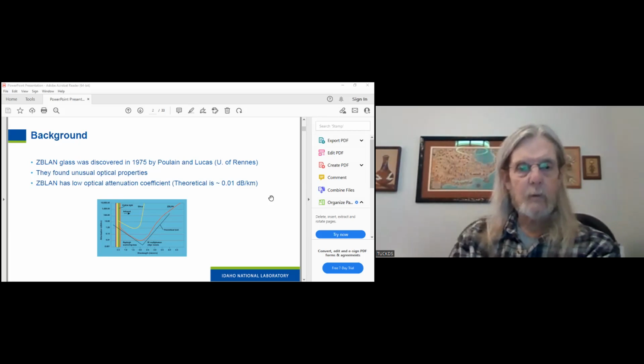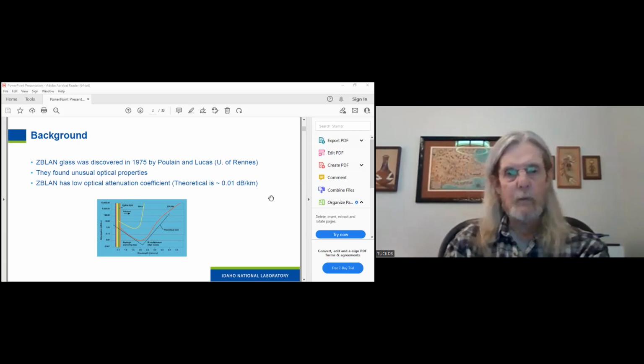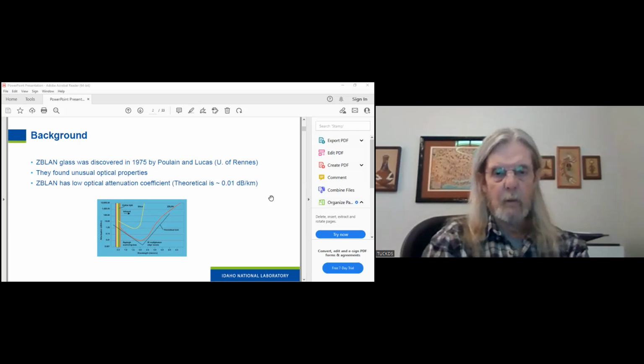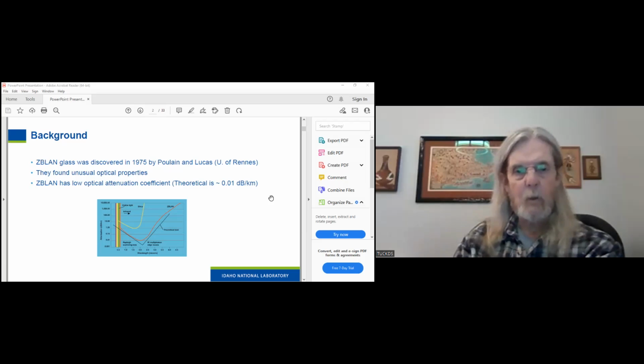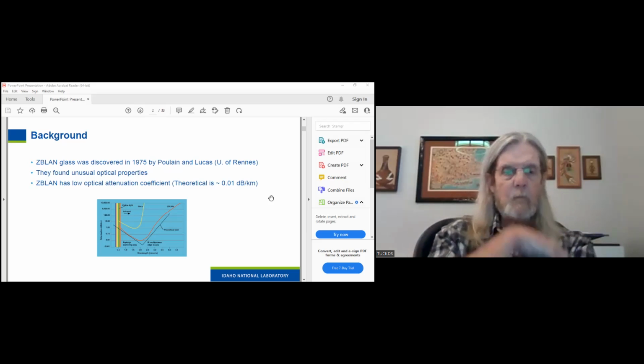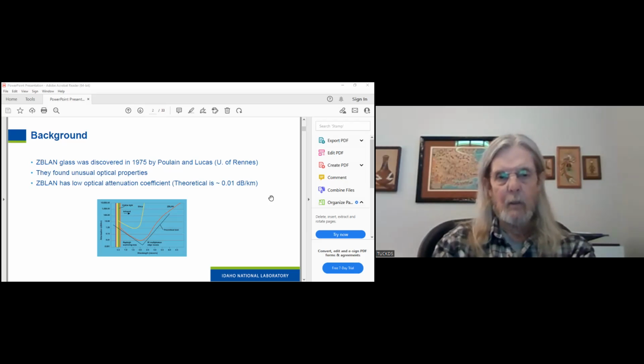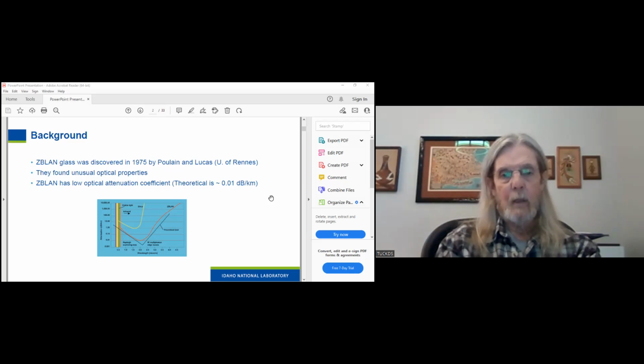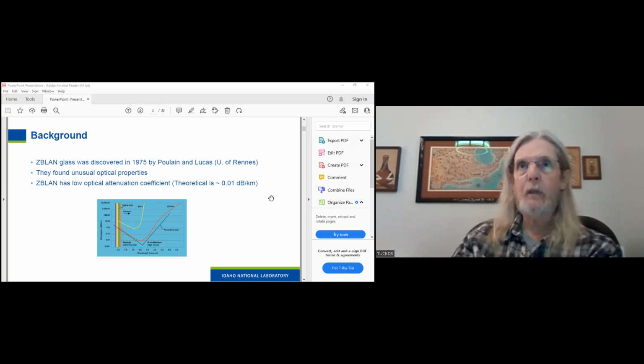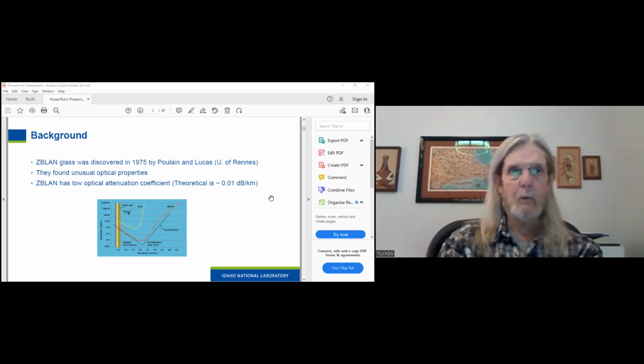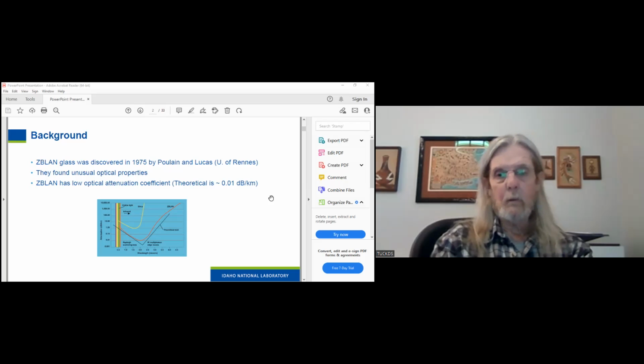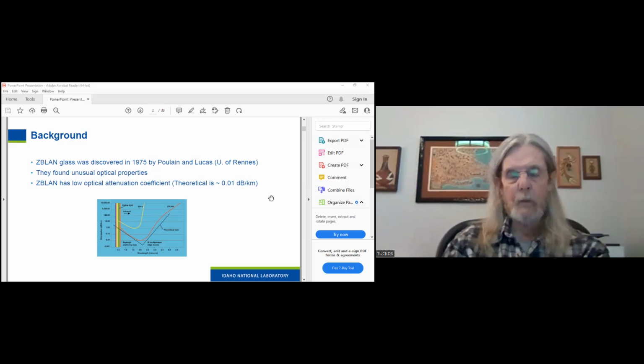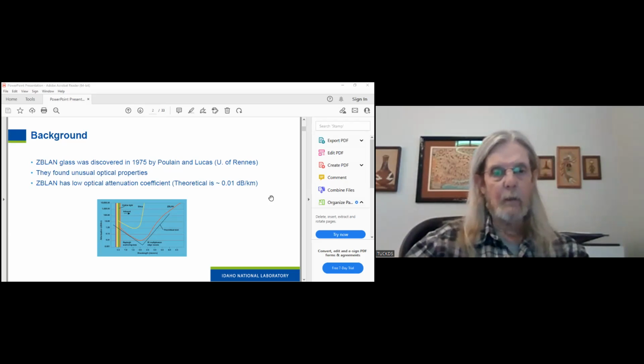And as you can see from the figure, attenuation coefficient versus wavelength for ZBLAN, there's a theoretical curve there, and also what has been measured to date versus fused silica. And one of the interesting properties of ZBLAN is that it transmits from the near UV to the mid IR. And that gives it some obvious applications for sensors. It also theoretically has a much lower attenuation coefficient than fused silica. And one of the things that was really investigated starting in the 80s was maybe replacing fused silica in long haul fibers for communications. But to date, that hasn't worked out. And I'll get into that a little bit.